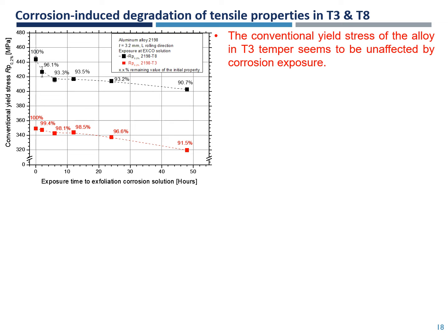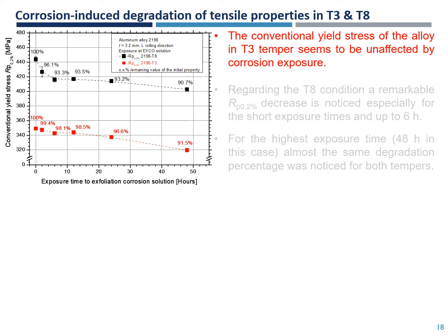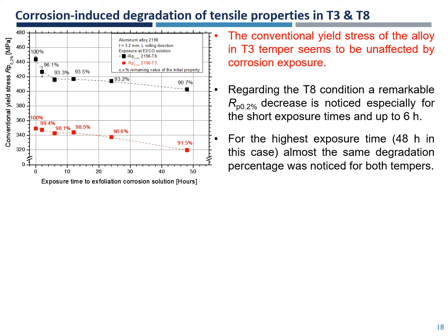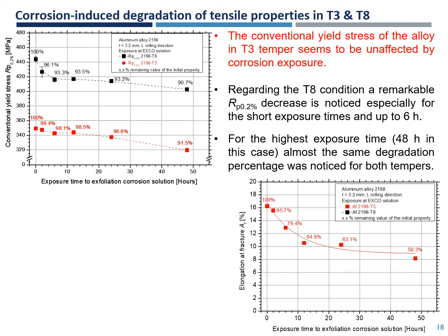Regarding the corrosion-induced degradation of the tensile mechanical properties in T3 and T8 condition, it was found that the conventional yield stress of the alloy in T3 temper seems to be unaffected by corrosion exposure time. Regarding the T8 condition, a remarkable conventional yield stress degradation is noticed, especially for the short exposure times and up to 6 hours. For the highest exposure time, almost the same degradation percentage was noticed for both tempers.